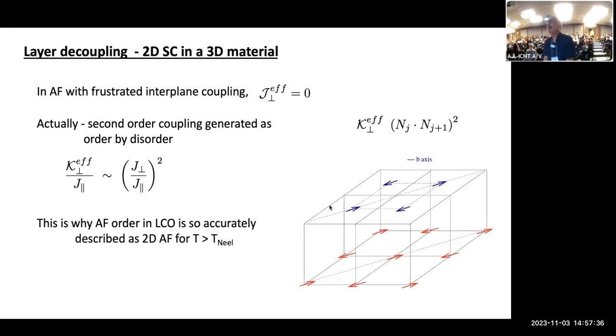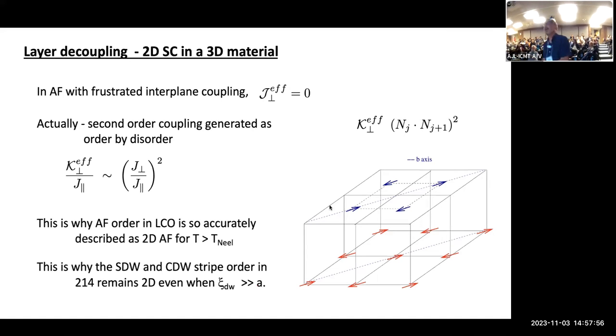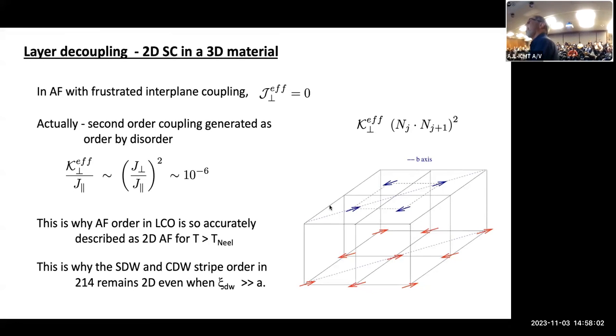Okay, and this is not only why you see 2D antiferromagnetism in lanthanum cuprate, but you actually also see rather long-range antiferromagnetic stripe order, which is totally uncorrelated in the third direction.